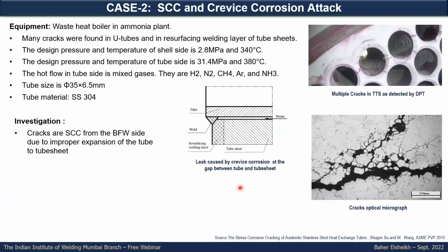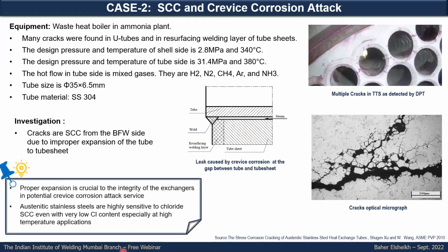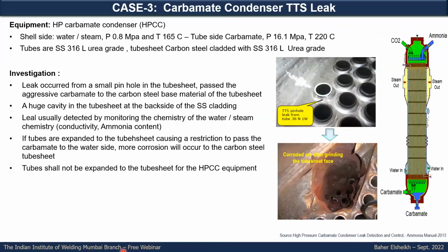This is the second case. It was a waste heat boiler in an ammonia plant, and cracks were found in many parts, including the tube-to-tube sheet joints. The tube material is austenitic stainless steel, and the cracks are stress corrosion cracking from the boiler feed water side, the shell side. It is due to improper expansion of the tube to tube sheet. That's why proper expansion to avoid crevice corrosion is highly crucial to the equipment in many cases, especially whenever you have material susceptible to stress corrosion cracking.